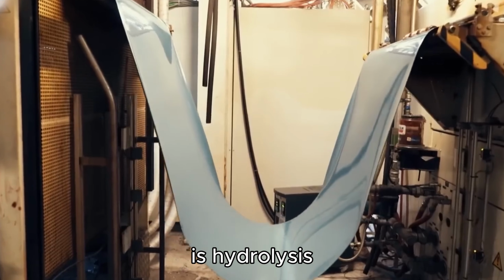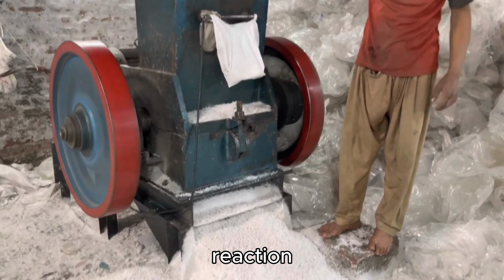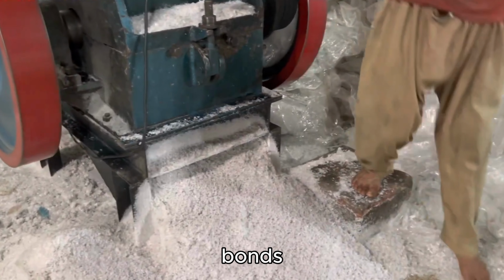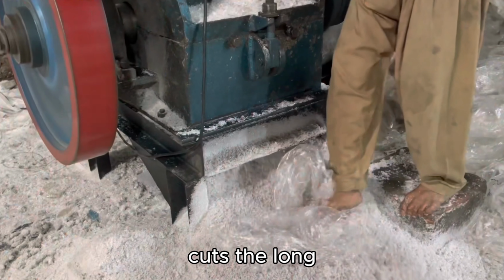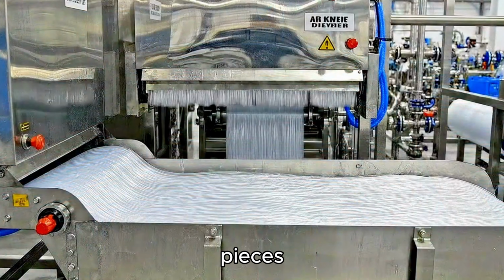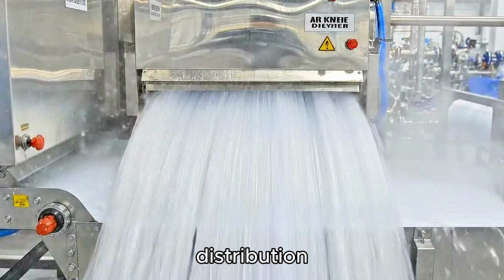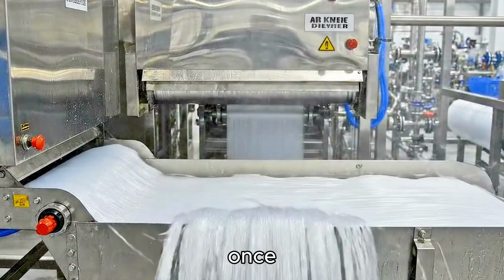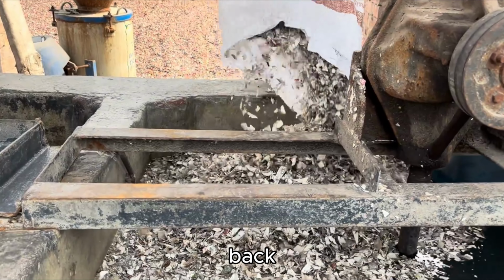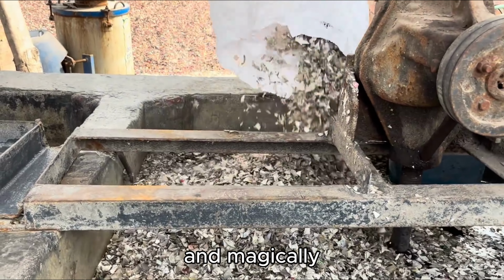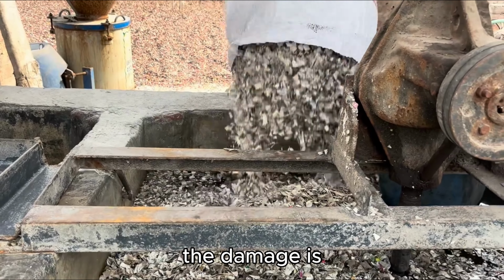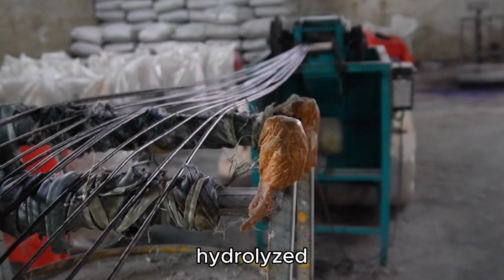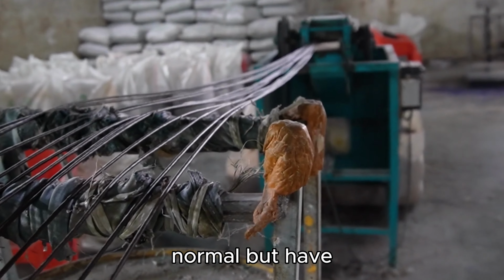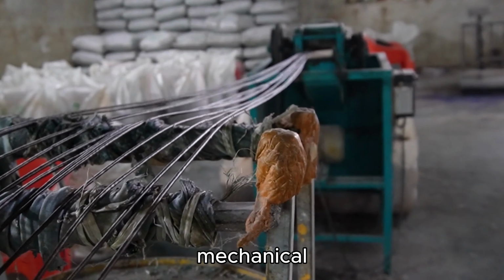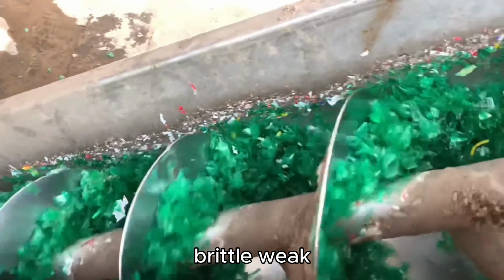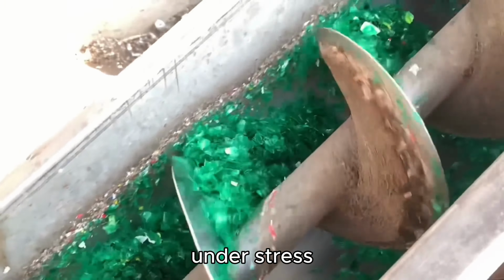The real danger is hydrolysis, a chemical reaction where water molecules break the covalent bonds in the polymer chain. This literally cuts the long polymer molecules into shorter pieces, affecting the molecular weight distribution of the material. Once that happens, there's no going back. You can't re-dry the material and magically reconnect those broken chains. The damage is permanent. Parts made from hydrolyzed plastic will often look perfectly normal, but have severely compromised mechanical properties. They'll be brittle, weak, and prone to failure under stress.